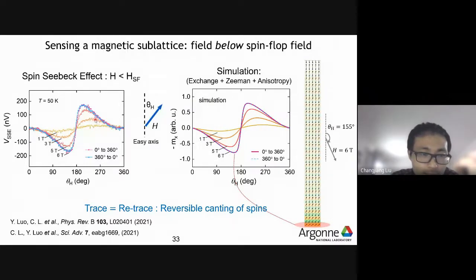And we found that this response is reversible as you rotate the magnetic field in the clockwise or counterclockwise direction, basically from 0 to 360 or 360 to 0. The traces are on top of each other, as shown by the green, the blue and the red data points for the 6 Tesla measurement.